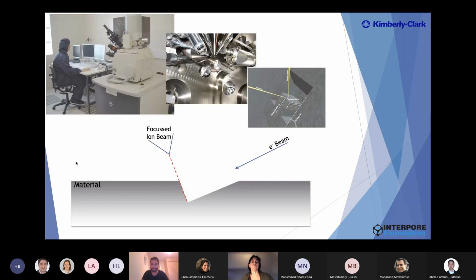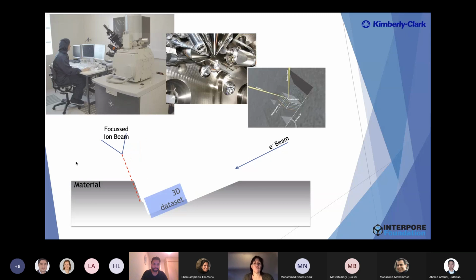If you're not familiar with this, the basic principle is that with the focused ion beam, you remove some material, you make an opening, and then with the electron beam, you take a scanning electron image. Then with the focused ion beam, you remove some more material and take another image, and by doing so, you're able to build up a 3D data set.